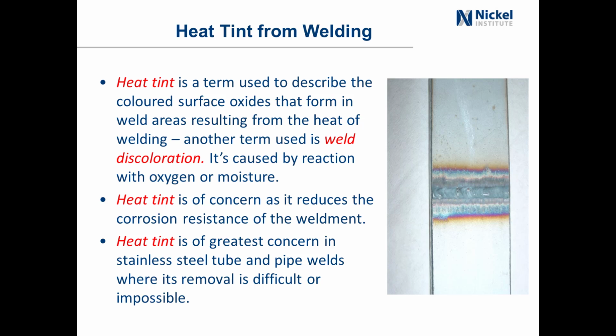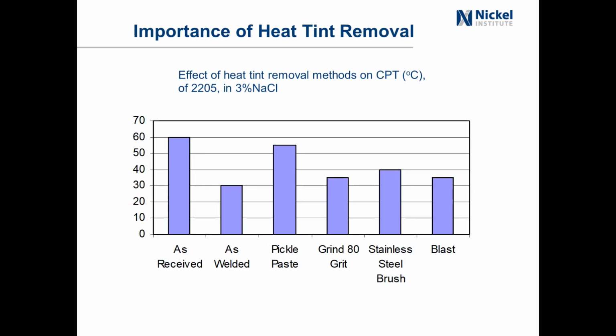And also underneath that, there's a thing called the chromium depleted layer. So this needs to be removed to ensure that you have optimum corrosion resistance in the weld area. Heat tint is of greatest concern in stainless steel tube and pipe welds where its removal is difficult or impossible.